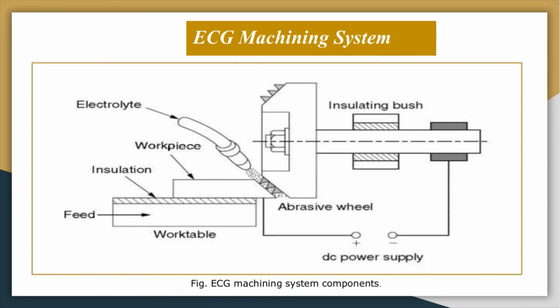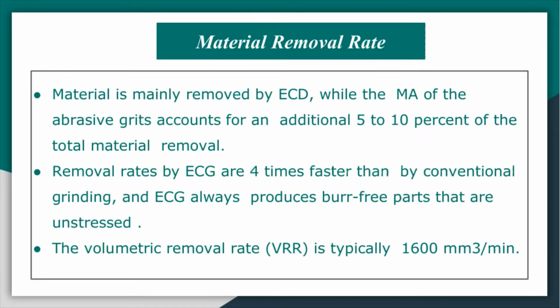The material is mainly removed by the ECD, while the mechanical action of the abrasive grits accounts for an additional 5 to 10% of the total material removal. So removal rates by electrochemical grinding are 4 times faster than by conventional grinding, and electrochemical grinding always produces burr-free parts that are unstressed. The volumetric removal rate, VRR, is typically up to 1600 cubic millimeters per minute. So this is the volumetric removal rate you will get from electrochemical grinding.